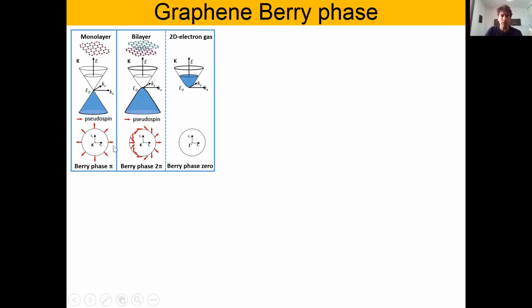Okay? So in graphene, this is closely related to the pseudospin and how the pseudospin rotates. In the case of the monolayer, the pseudospin makes one turn, rotates once. This is what is called the pseudospin winding. Rotate once along the K point. So it corresponds to a Berry phase pi. When we go to the bilayer, the pseudospin rotates twice around the K point, so it corresponds to a Berry phase 2 pi. In contrast, if we compare to a standard 2D electron gas, as we saw in the copper at the beginning, there is no pseudospin, so this corresponds to a trivial 0 Berry phase. Okay, and this Berry phase is key for graphene.